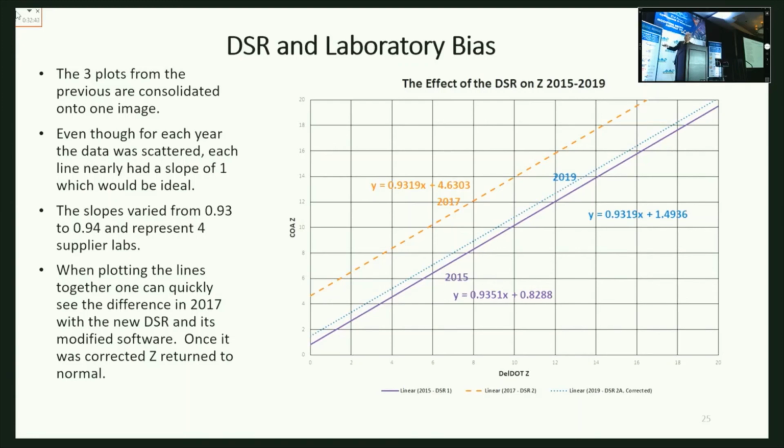2015 was the old DSR. 2017 was the new DSR. You see, there's a big difference. With anything like this, you see the data doesn't look the same, but after a while, you start plotting it out and can see the difference. So I talked to the manufacturer. He said, oh, yeah, our applications lab didn't like the shape of the curve and changed this, that, and the other, thinking to make it better. Well, it changed how it behaves. Rheologically, probably what they did made sense, but since we're dealing with the standard, it's not the way to go. You'd have to change AASHTO.